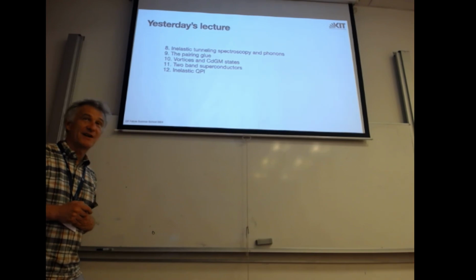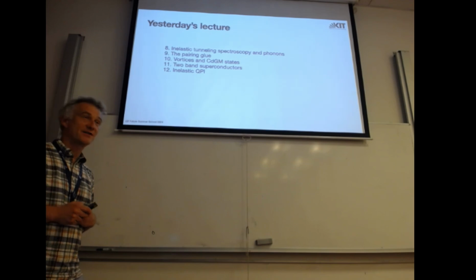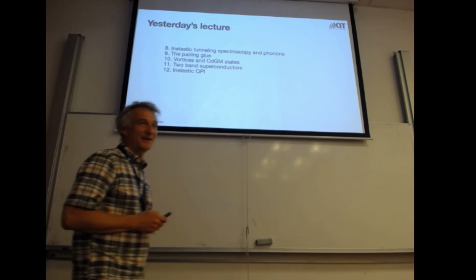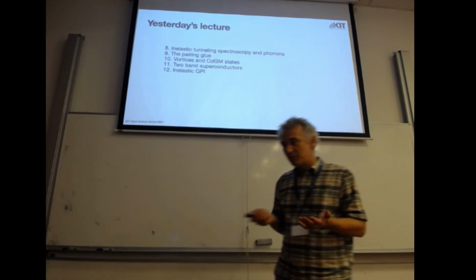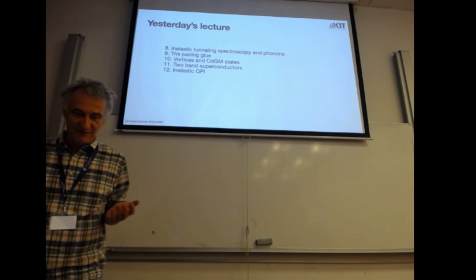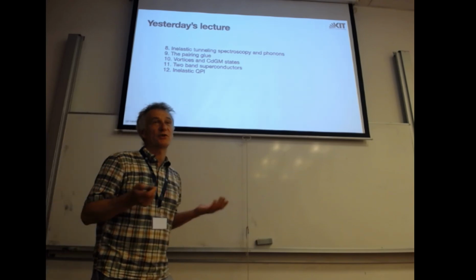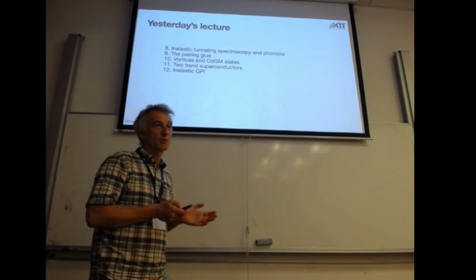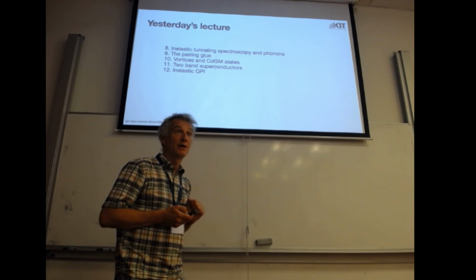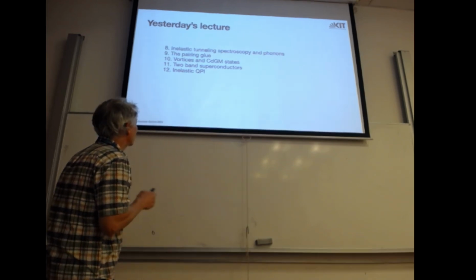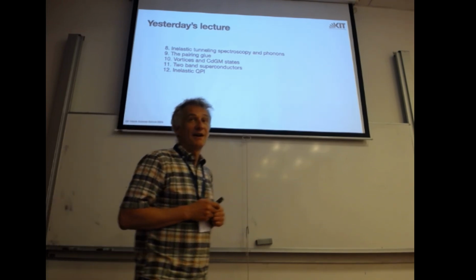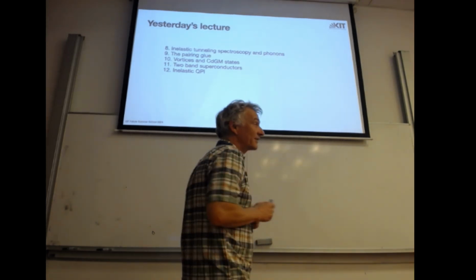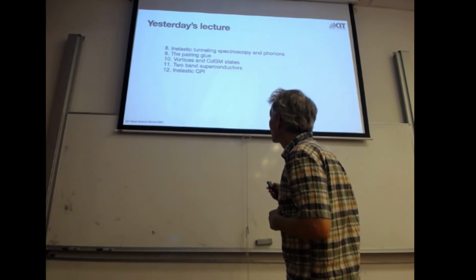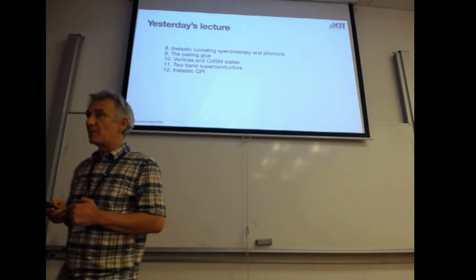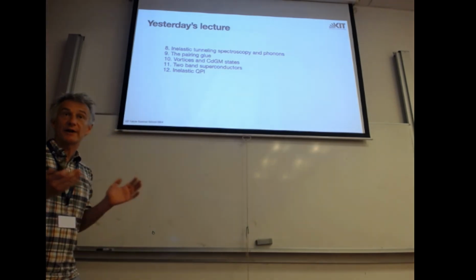And I showed you examples. I cheated a little bit there because I renormalized the electrons, but I didn't renormalize the phonons. But typically there is a big theory that they are pretty separate. The electrons become superconducting, but the phonons do not change too much from going from the normal to the superconducting state. This will be completely different later for the unconventional superconductors. Then we looked at vortices and CdGM states. I showed you some unpublished data on two-band superconductors, which were not inelastic, and I showed you really very new data that maybe we can also map phonons by their inelastic signature if they are in a box.